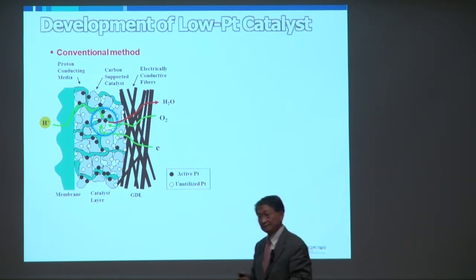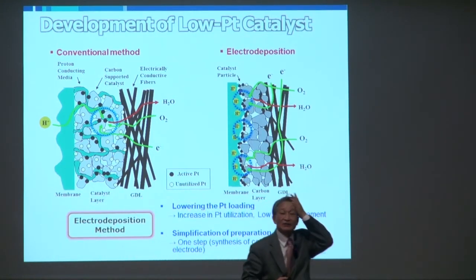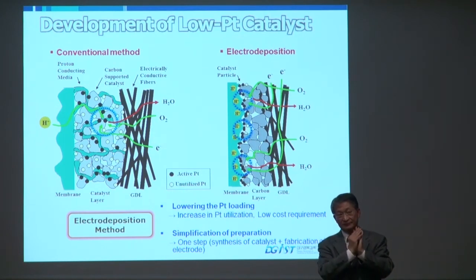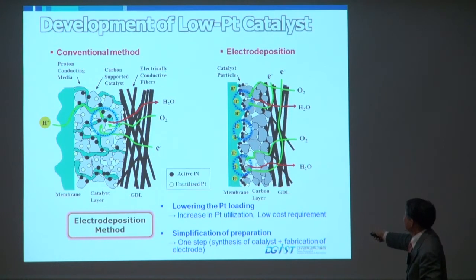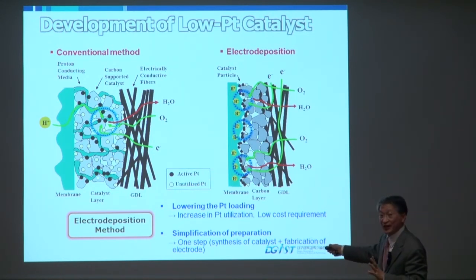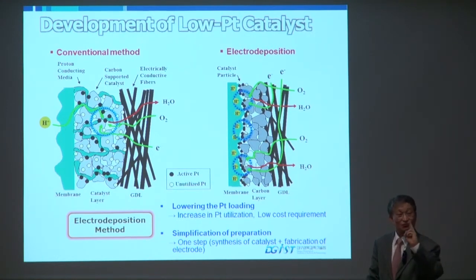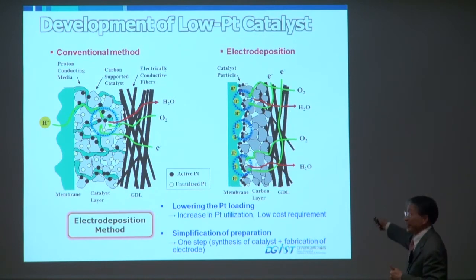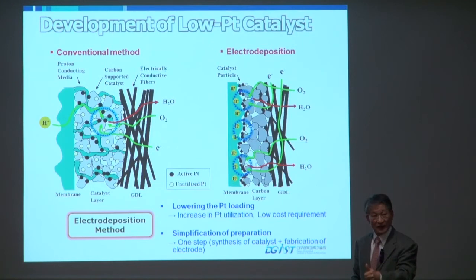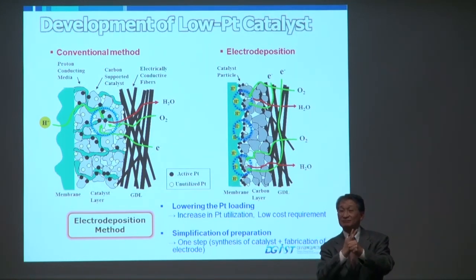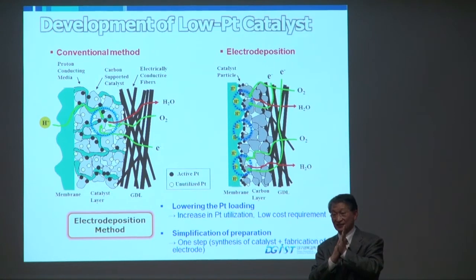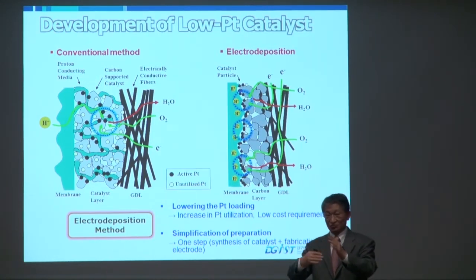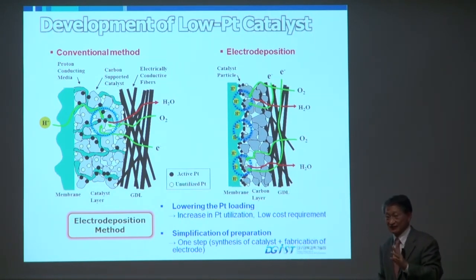So we developed a new method for electrochemical deposition. Electrochemistry occurs only at the surface. Okay? Then it looks like this. So the utilization for platinum site should be much greater than this one. But there are two problems. First, the gas diffusion layer is a hydrophobic layer. Hydrophobic means the water cannot easily be in contact with the surface. That means electrochemistry in aqueous media does not occur on hydrophobic surface layers. So there are some problems to be solved for this hydrophobicity of the gas diffusion layers.